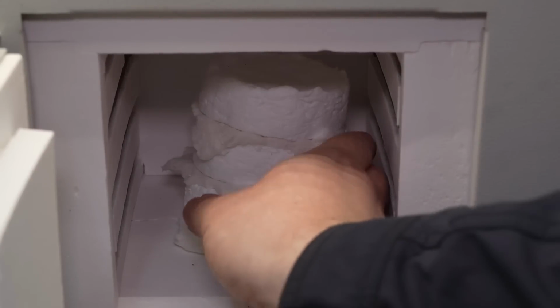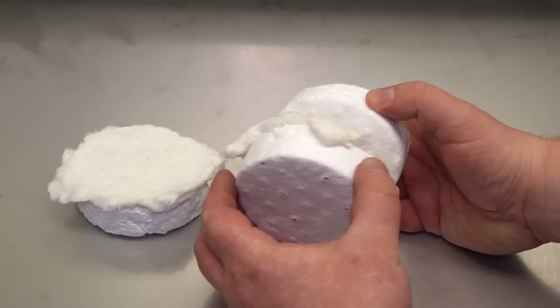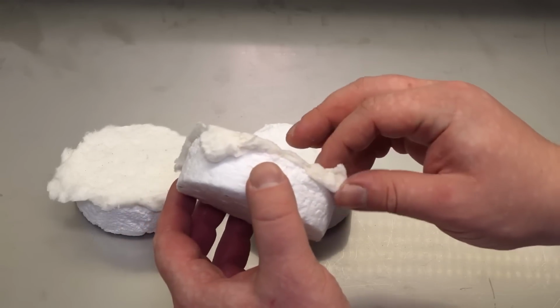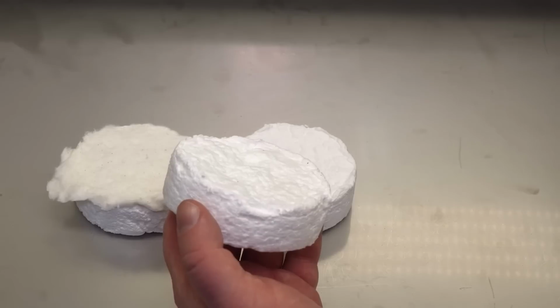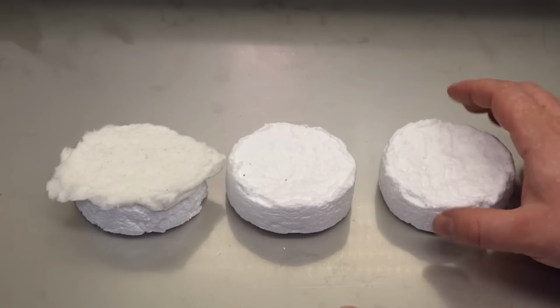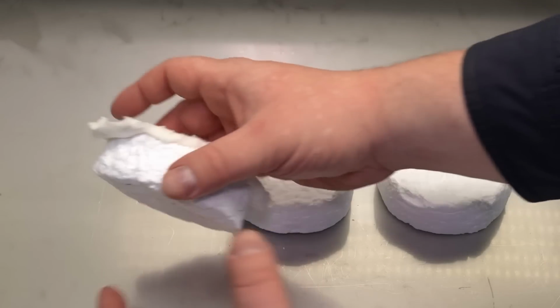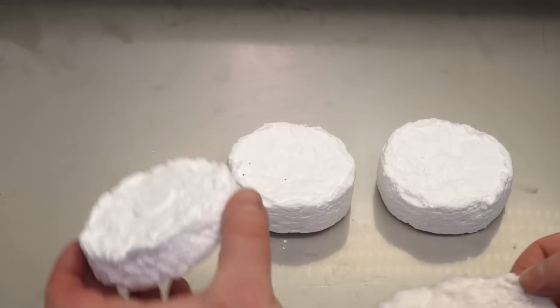After the furnace cools down, I take out the blanks, and in my opinion, they turned out just perfect. During sintering, all the cracks simply disappeared, and the resulting thermal insulation samples turned out to be very light, without internal voids and quite even.